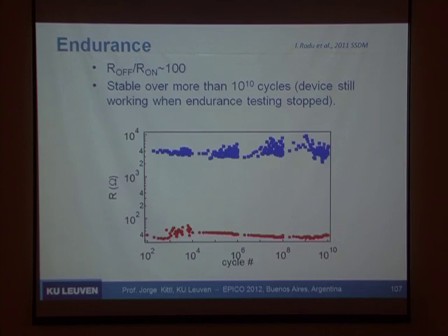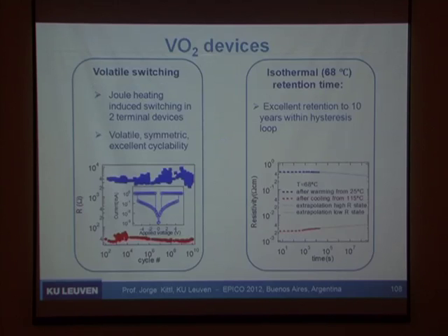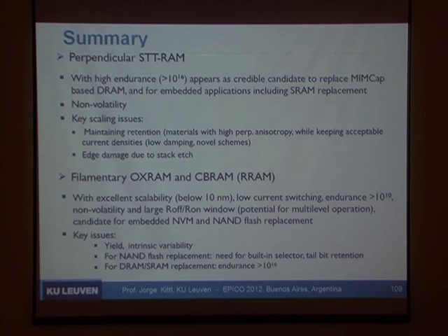I believe. And why this could be interesting, one of the things is endurance is extremely high. We never saw anything fail in endurance, actually, tested. Well, the hafnium oxide showed you 10 to the 10 with a huge effort to get there, right? Balancing this, with this material, whenever we switch, we can switch forever. So that was the interesting thing. Okay, I think that's more or less the end of my talk.